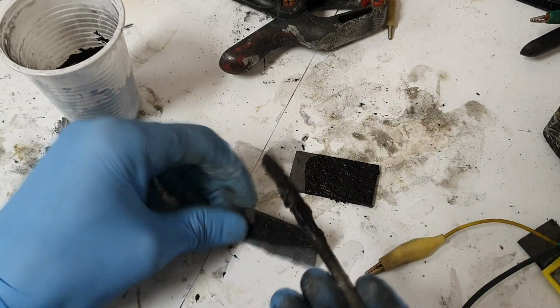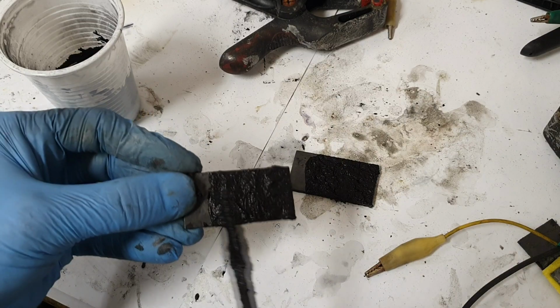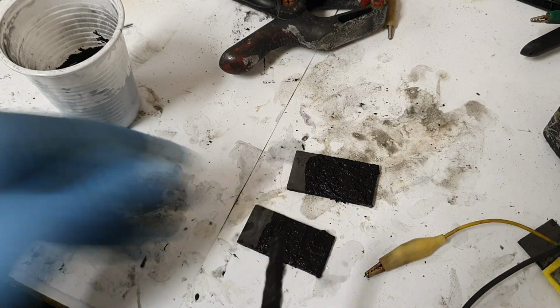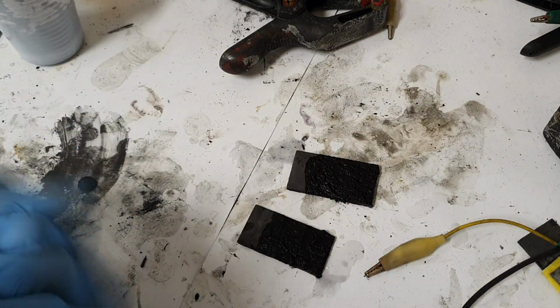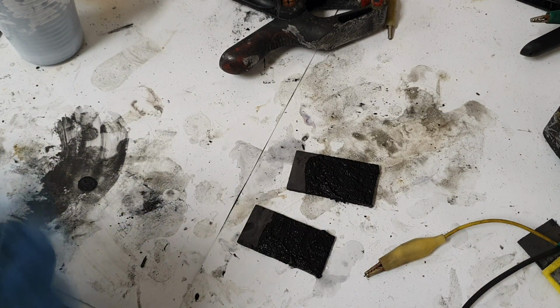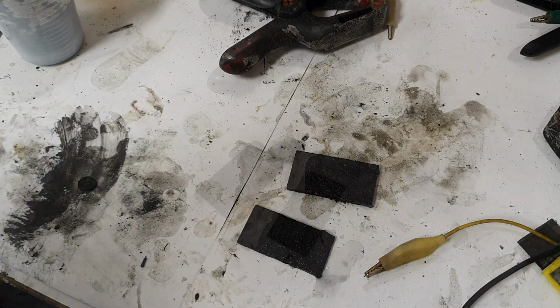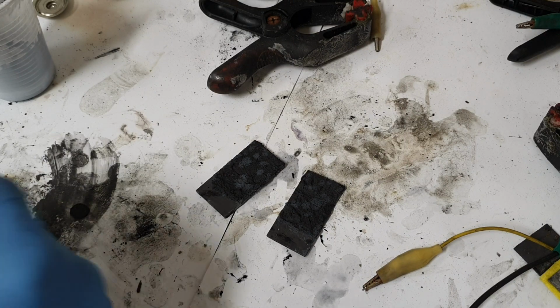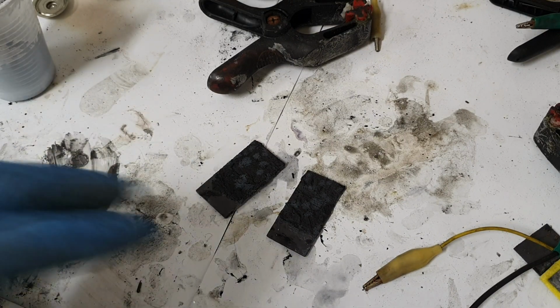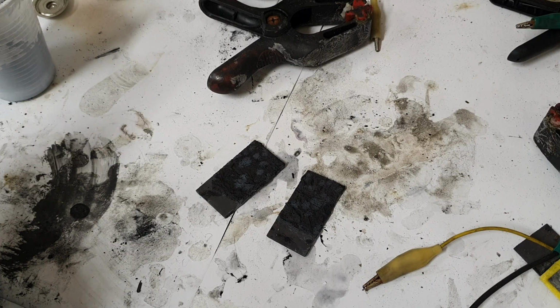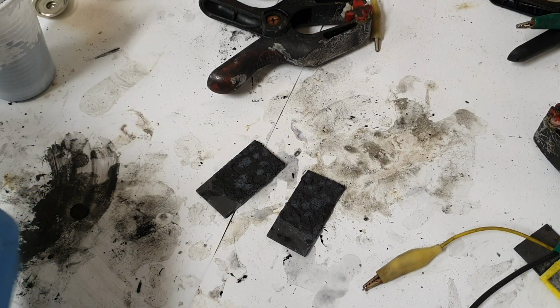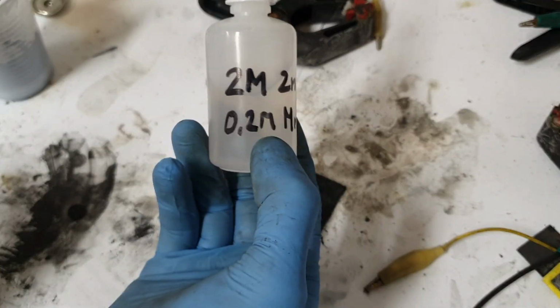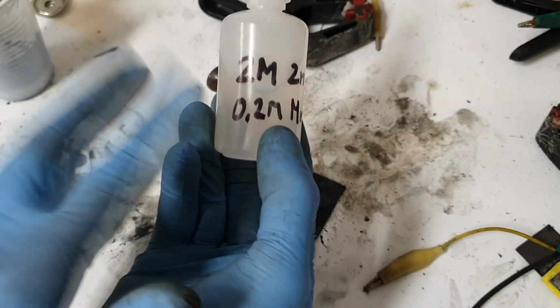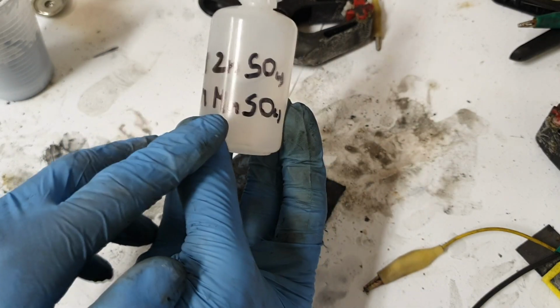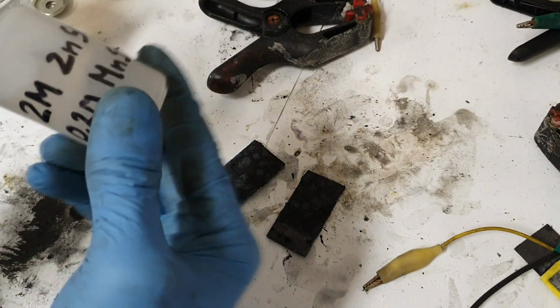Okay, this will be enough. Now I will dry these two electrodes and then I will make a cell. So the electrodes are dry and now I will put some electrolyte on the top so that the electrolyte will soak into the active material. And the electrolyte is 2 mole of zinc sulfate and 0.2 mole of manganese sulfate.